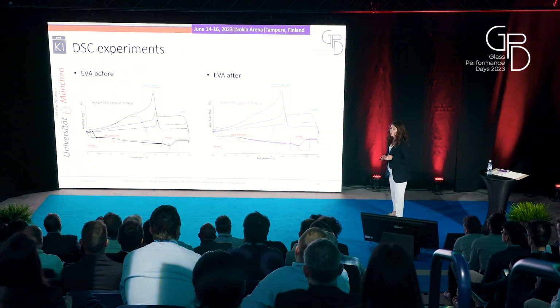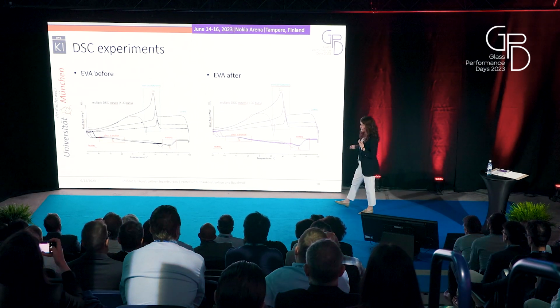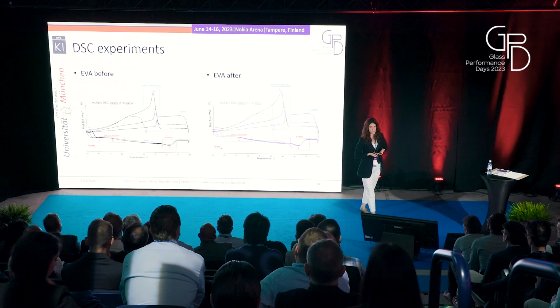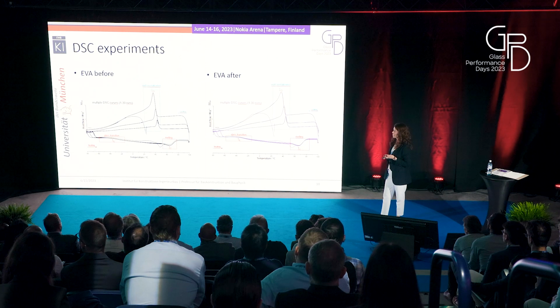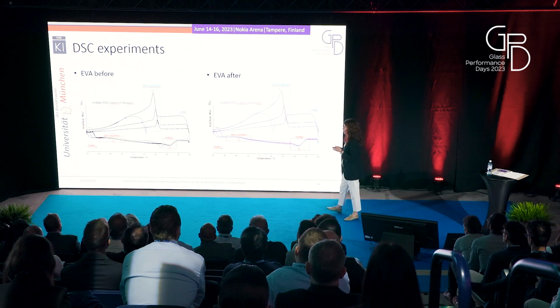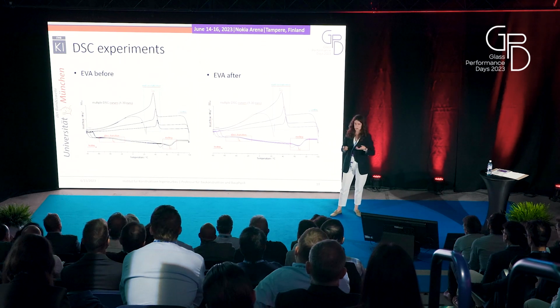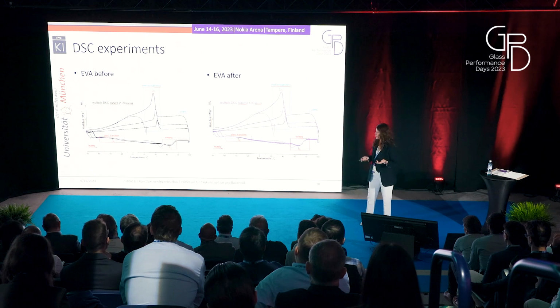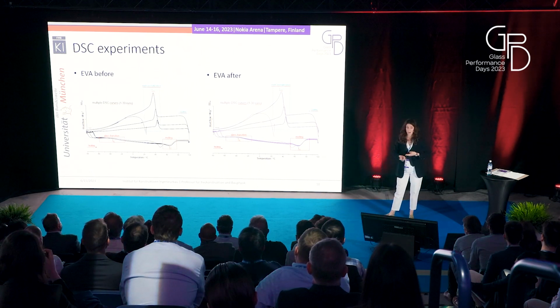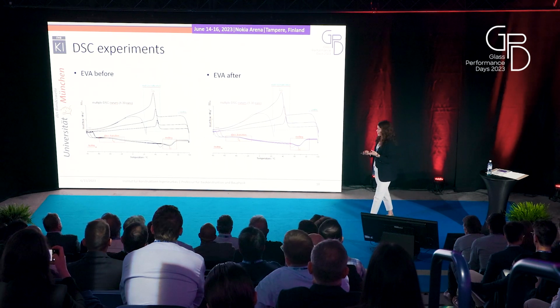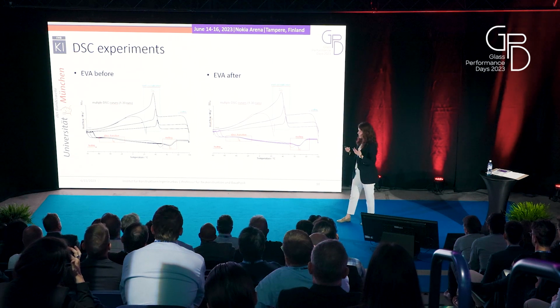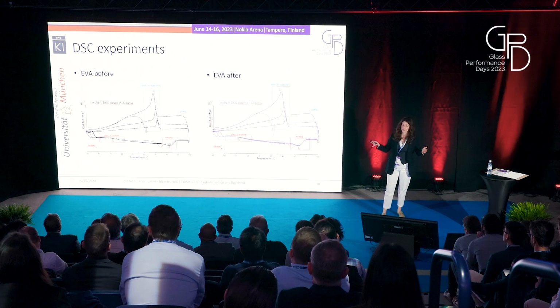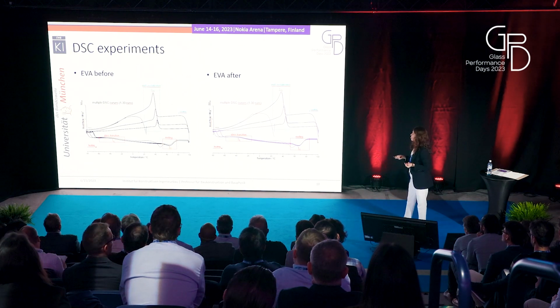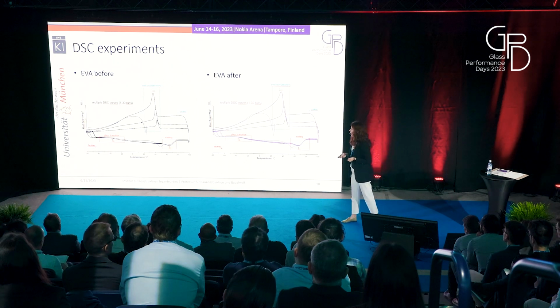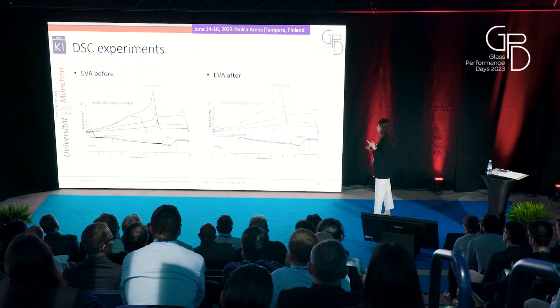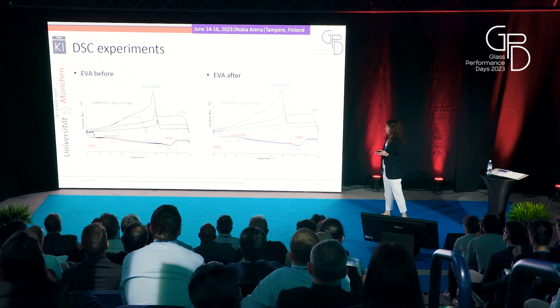Why did we use this range? Because we wanted to put the interlayer into a range that could really occur during service in general. It's not uncommon that laminated glass, some kind of glass structure which is outside, experiences temperatures that go down to -20, or that the temperature in a glass goes up to +40, 50. So we wanted to put the interlayer into these situations that could really happen in real life. And on the Y axis is the heat flow. And here we can also see these three important properties of the interlayer that I mentioned earlier.